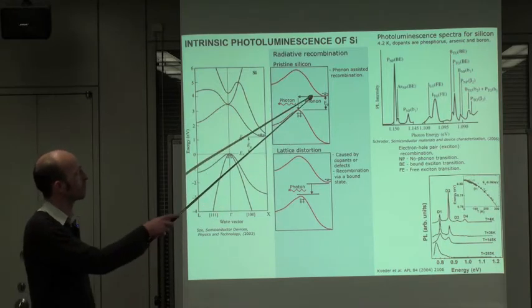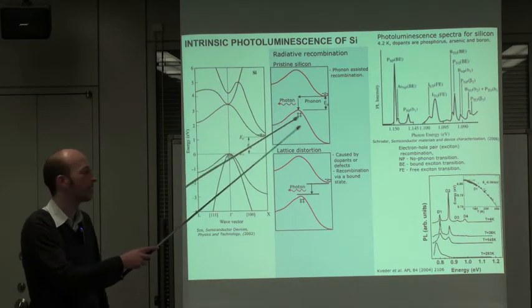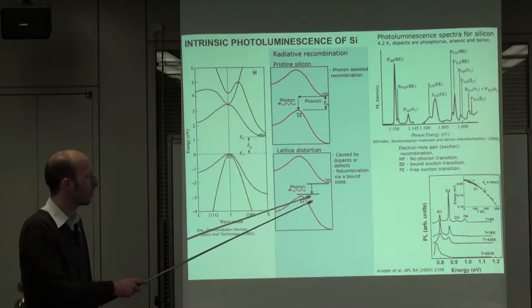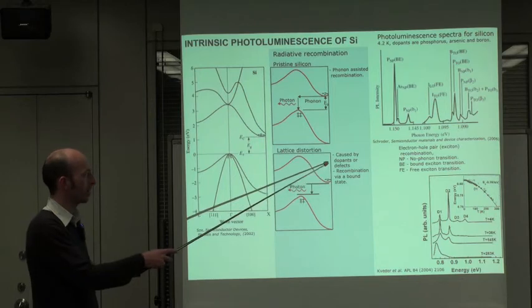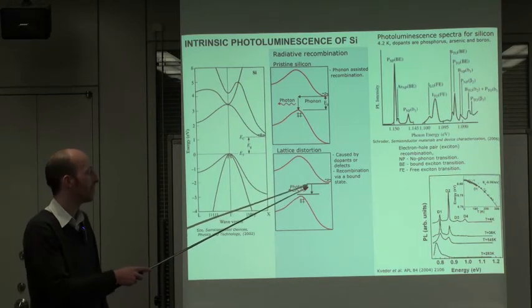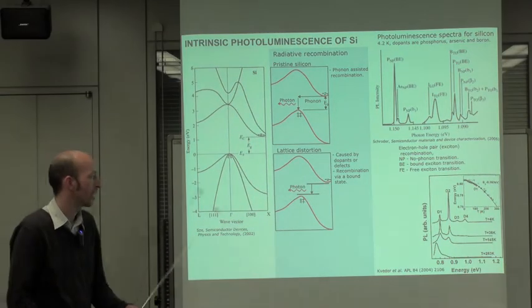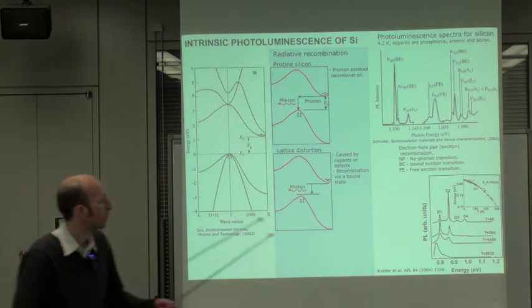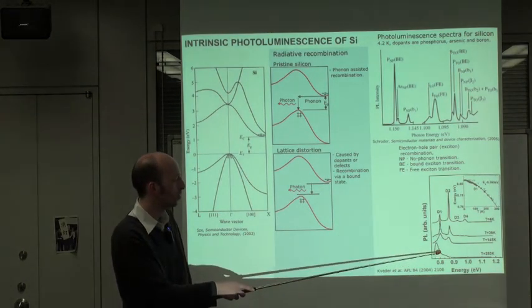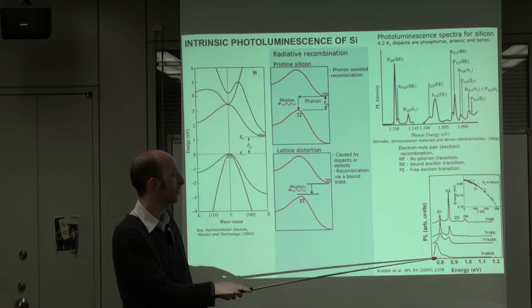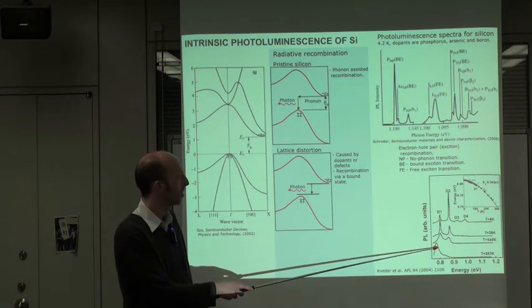But it's usually phonon-assisted photoluminescence. But if you distort the lattice by introducing dopants or defects, you might get a direct band transition. I think this paper came out in 2004, which showed room temperature luminescence through dislocations.